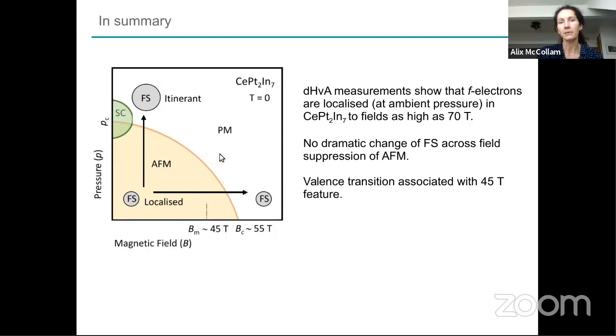But we do see now this transition that we think is related, well, not transition, but probably crossover related to valence, a change in valence in the material about here. And something has to happen in this material because we have a large Fermi surface up here and a small Fermi surface over here. So we know that there has to be some kind of transition in the material somewhere in this region of the phase diagram. And I think I should stop there. Thank you for your attention.